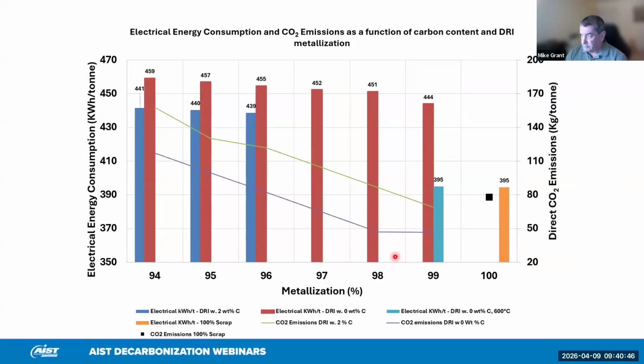Now, natural gas-based DRI puts carbon in the DRI, which theoretically shows it has benefits, but in reality, natural gas-based DRI is very difficult or expensive to go much above 96% metallization. As Martin explained, 99% metallization is very achievable with hydrogen-based DRI. So really, when we're comparing carbon-based DRI with hydrogen-based DRI, you compare 99% with 96%, and you can see here that